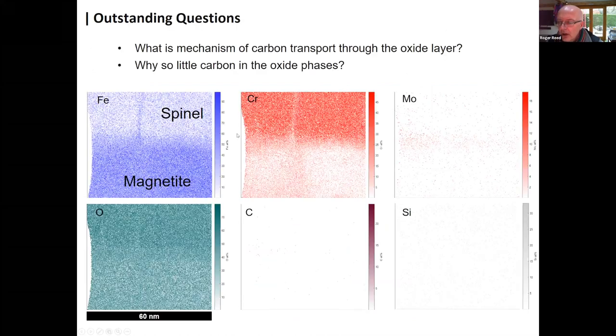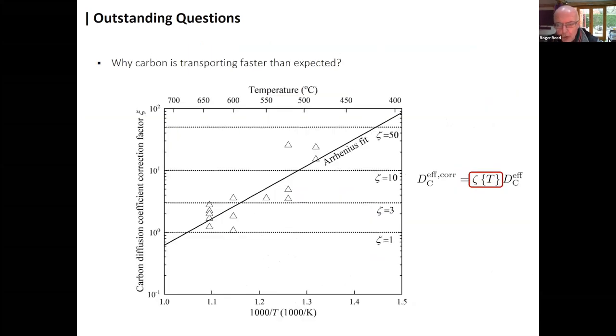So as always with science, there are outstanding questions, which Harry, of course, probably can shed light on. One of the issues is the mechanism of carbon transport through the oxide layer. In all of our experiments over 6 or 7 years, we have never been able to find any carbon dissolved in the oxide species. Spinels, magnetite, these are atom probe data. We don't find any carbon there, which leads us to kind of wonder how the CO2 or carbon can migrate through the oxide.